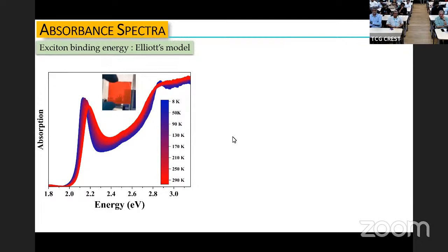But before that, let's talk about the excitonic binding energy, another point that I've talked about. This time we need to do the experiment in a slightly different way. These are true absorption experiments on a thin film, as shown over here, as a function of temperature. This is the excitonic absorption, and this is the free carrier absorption. You can fit them with a model called the Elliott model, where the excitonic binding energy is a parameter. So the best fit tells you what the excitonic binding energy is.